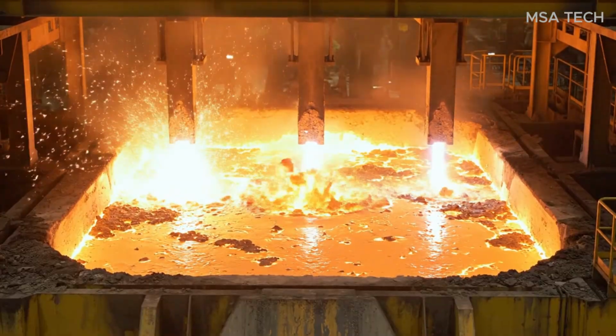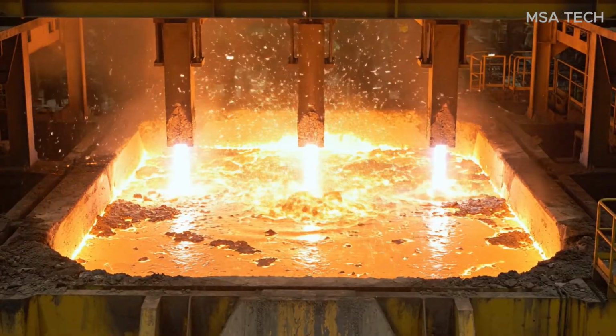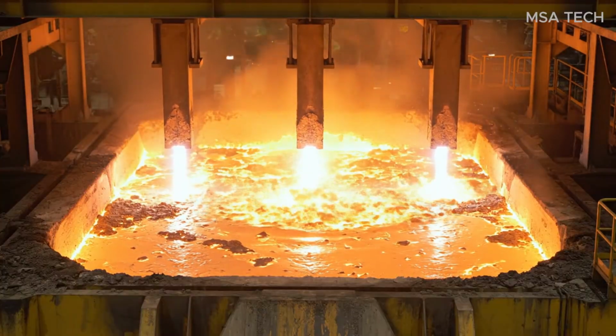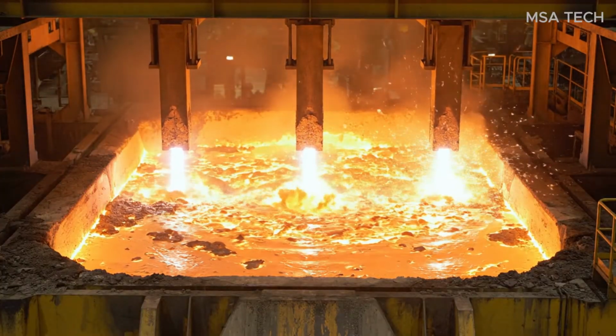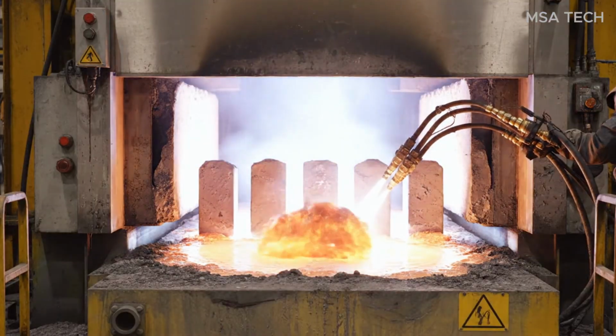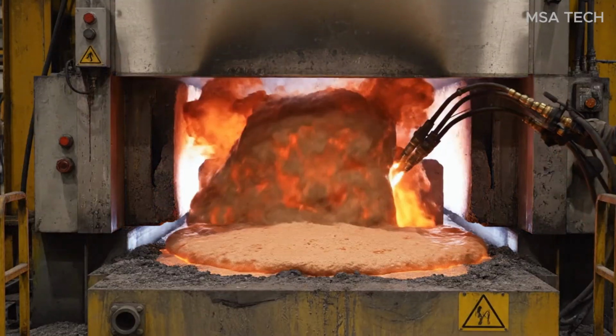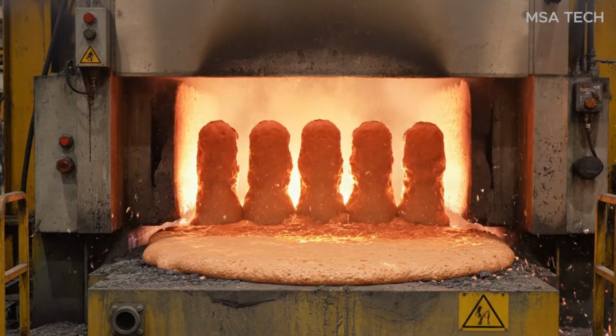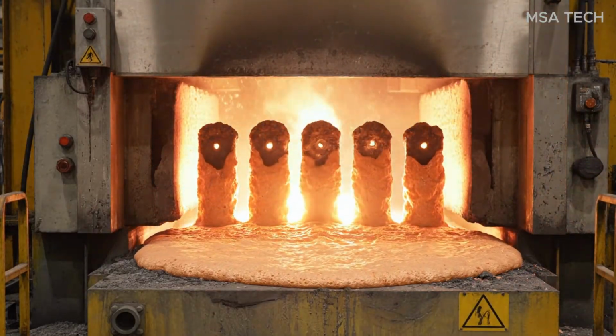Once the solid scrap collapses, the furnace holds a flat bath of liquid steel. The temperature now approaches 2,900 degrees Fahrenheit. Carbon is injected to create a foaming slag. This thick blanket insulates the arc, capturing the heat within the metal and protecting the furnace walls from damage.